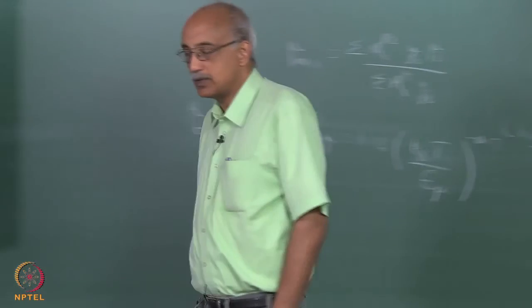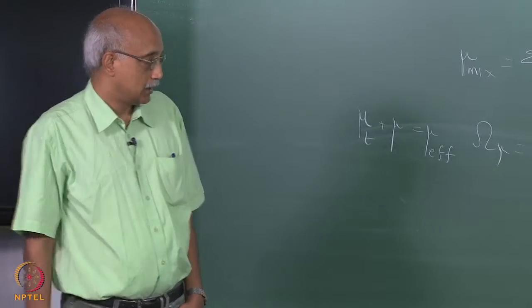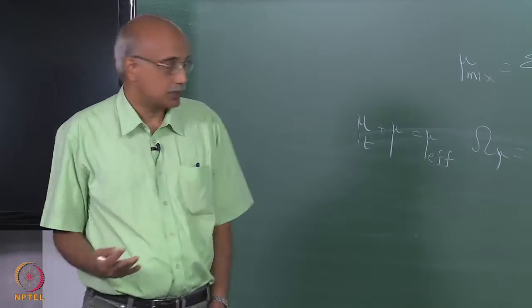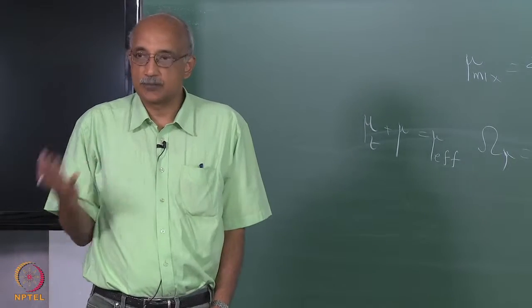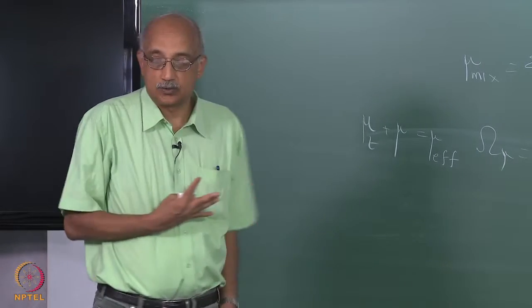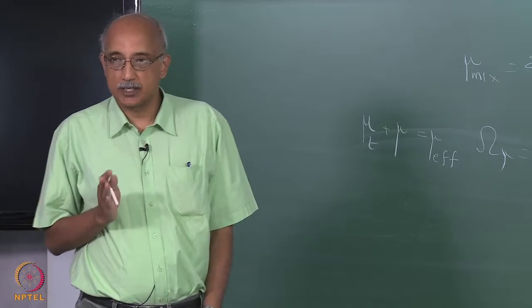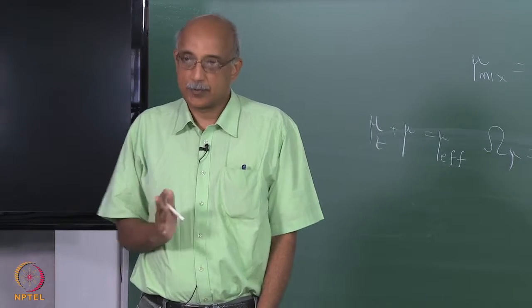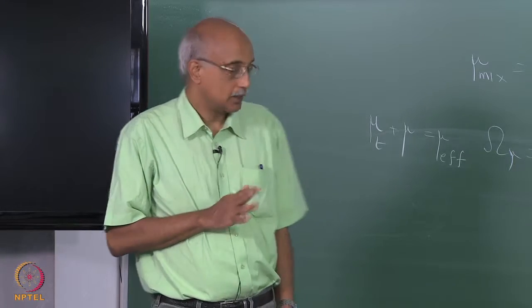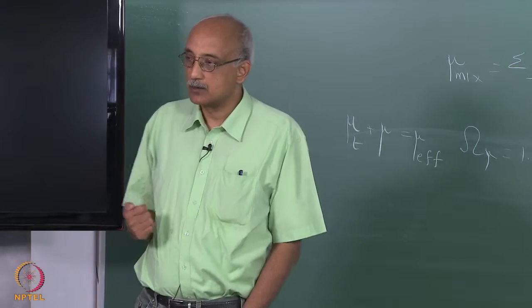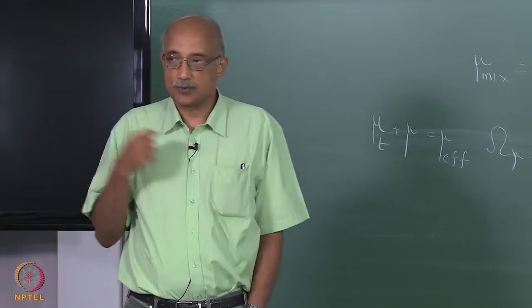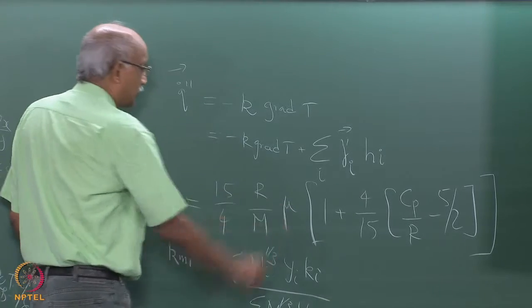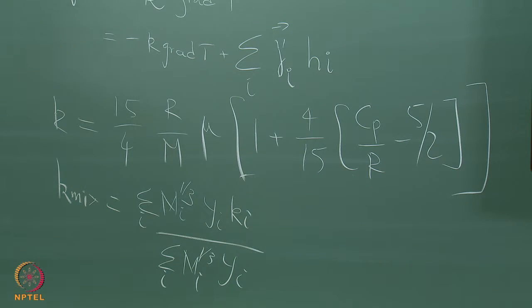So, thermal conductivity as well can be measured from experimental observations. Of course, thermal conductivity is fairly easy to measure simply by measuring temperature gradients, which is much easier to measure compared to velocity gradients obviously. So, thermal conductivity is much easier to measure experimentally. So, typically the route that one would take, if you do not want to calculate mu and K from first principles, is to run experiments to measure K and then use this formula. Now that you know K, you can go back and estimate mu, right? Because as I said, viscosity mu is very, very difficult to determine through experimental observations, whereas thermal conductivity can be obtained much more easily.